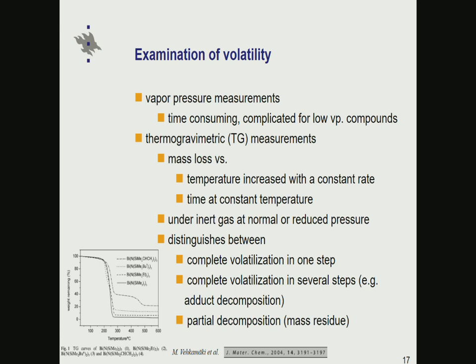This can be done under inert gas at normal pressure or under reduced pressure. The normal pressure measurements are much more simple to do, and as a result these are quite often, for example in our group, done at atmospheric pressure, even if they are not exactly so relevant to the ALD conditions where we are working under reduced pressure. Anyhow, no matter what the pressure is, from these curves we can distinguish whether there is a complete